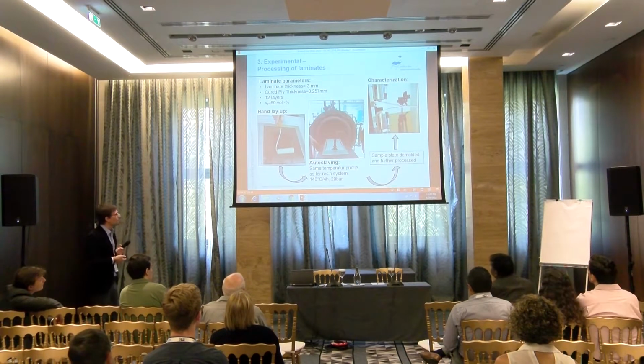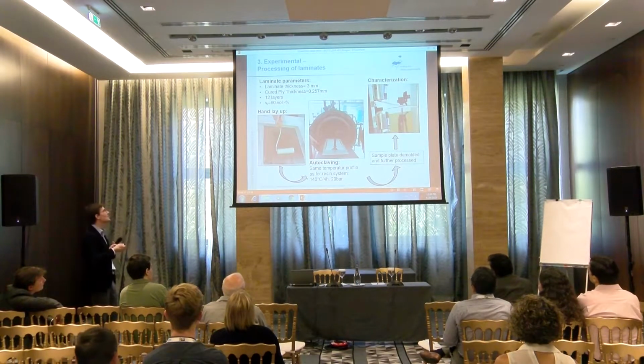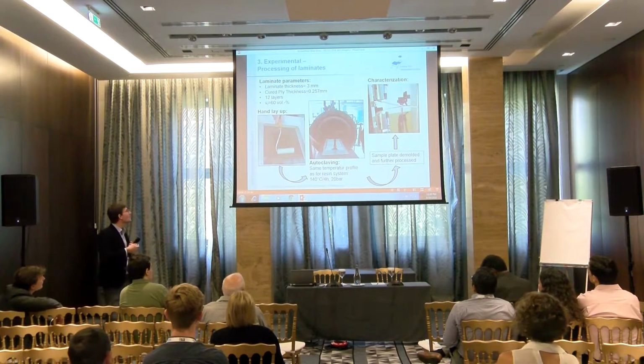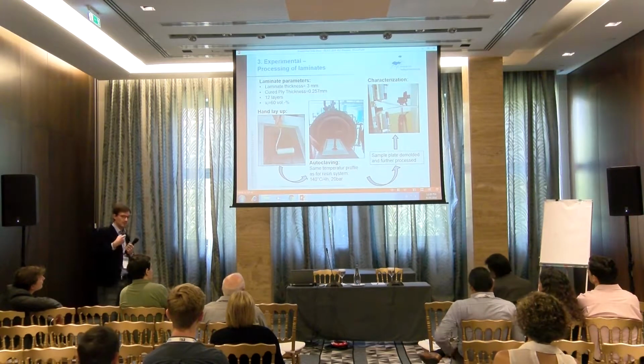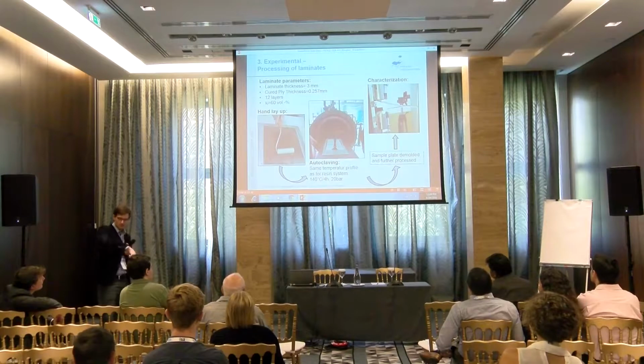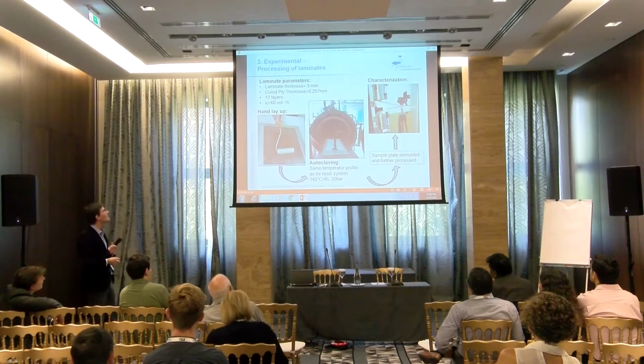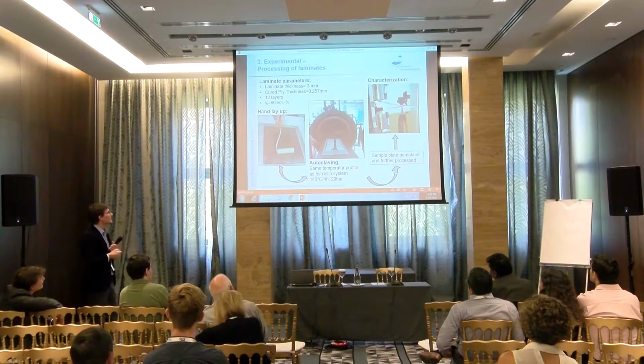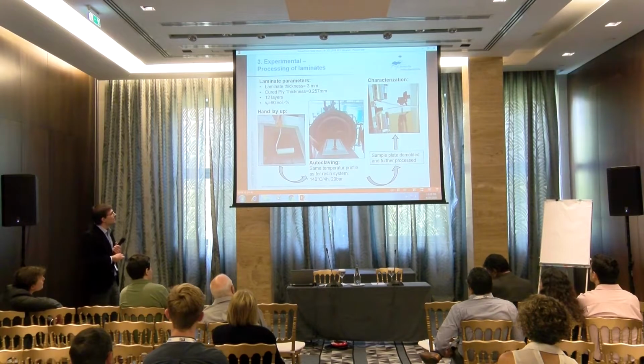Processing of the laminates was not done similarly, but closely related. We laid up the fibers in unidirectional direction, 12 layers, hand laid up, so resin was put on a single ply, and then another ply was added, and so on. In the end, we obtained a laminate thickness of about 3 millimeters and 60 volume% of fibers. The materials were autoclaved and afterwards tested.